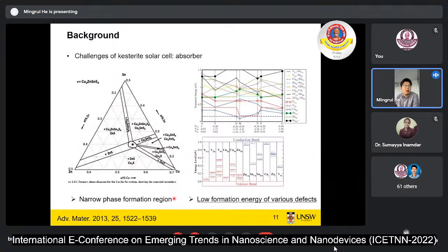Fortunately, this won't be too difficult to control. Once we get a good composition region, where we optimize the composition and the annealing condition for the formation of CZTS, normally we can get the highly crystallized pure CZTS phase with less secondary phase. So this is okay so far. However, because of the nature of the material of CZTS, it is quite easy to form different defects.